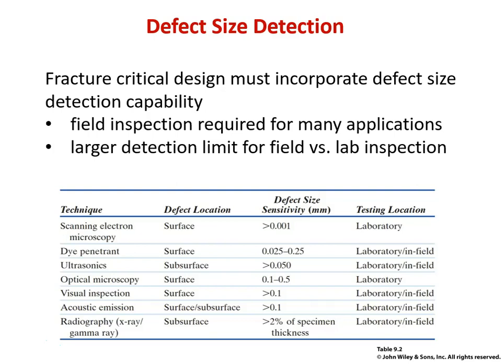Fracture critical design must incorporate a defect size detection capability. It does no good to simply say you must use a material with this K1C if you don't specify the largest allowable flaw size. I mean, obviously, if you can't detect flaws that are very big, you better go with a material with a higher K1C in order to accommodate a given design load. They're related. Now we know how they're related.